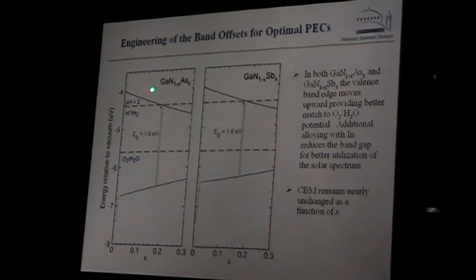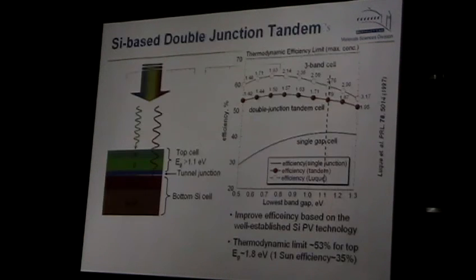So we have to operate somewhere in this region, where the conduction band is above the redox potential of hydrogen. However, antimony would be better because it pushes it more here, so we could operate still at 1.6 electron volt. This would be a good agent, and still have redox potential below the conduction band edge. So there are many options, and we are now concentrating on this one because, as I told you, we synthesize gallium nitride arsenide in the whole composition range, and this is the active area. We were not able so far to synthesize antimonides. So again, it comes to the point that we may try to use it for different purposes as well.